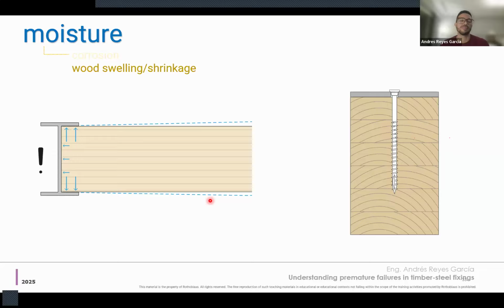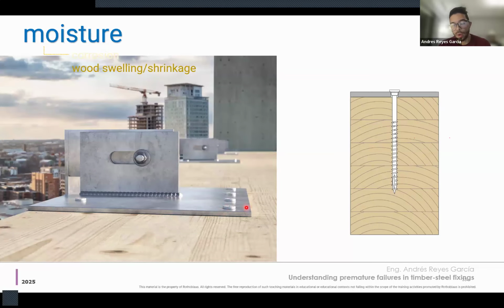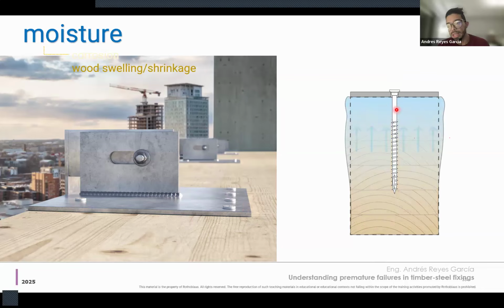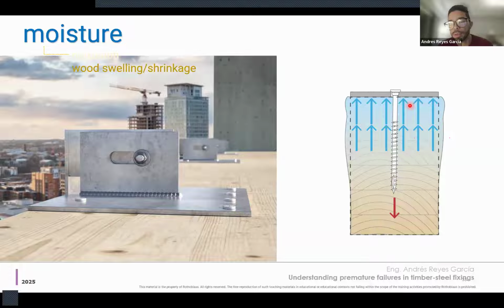But to explain more or less what can happen, and that makes it a bit more problematic, is that in a case like this, or in a job site that comes into the connection, then we have some forces from the deformation while the tip of the screw is in a drier place, which has higher mechanical performance of the wood. Thus, the screw has higher withdrawal capacity compared to the rest. And then you have a differential relative deformation. So the screw here is very stiff. Then it finds another stiff element as the plate, and the wood will deform close to the head, pushing the screw in the upper direction.